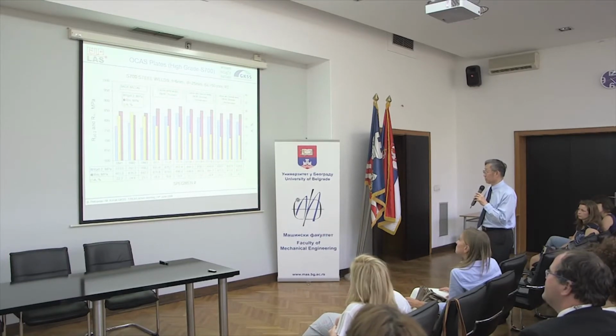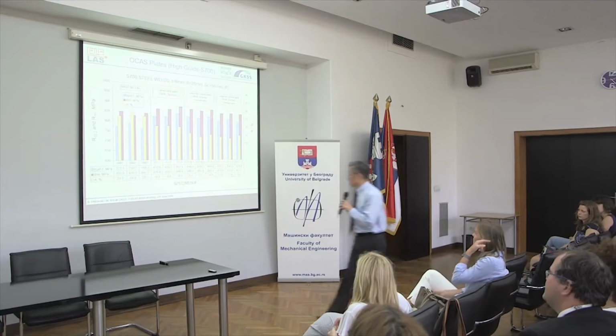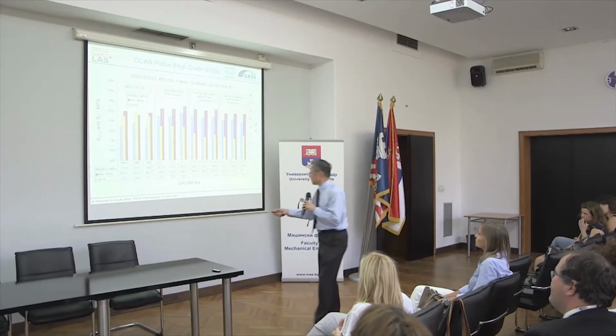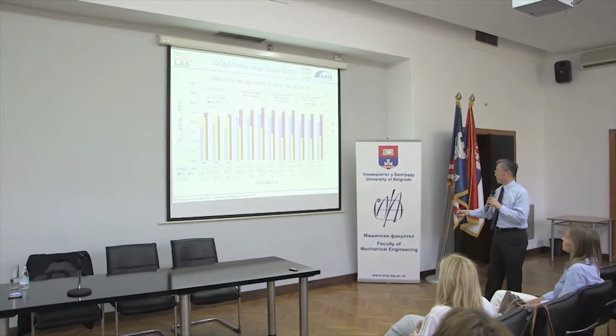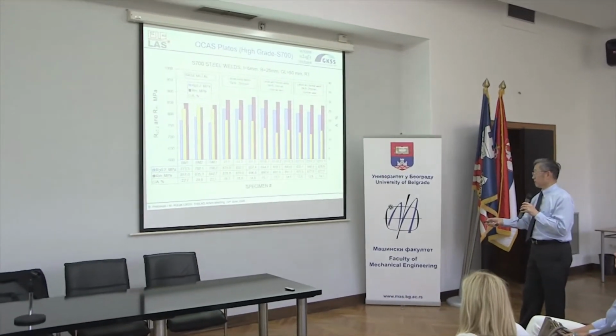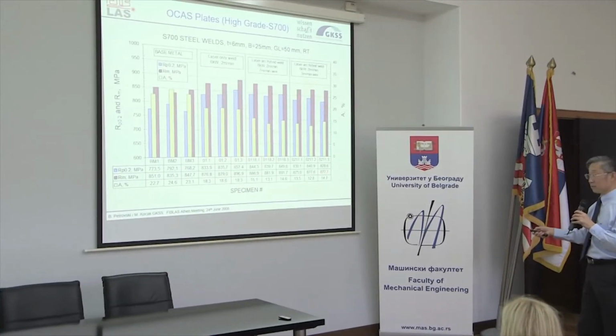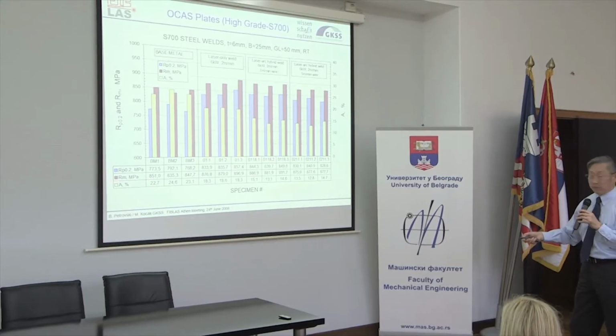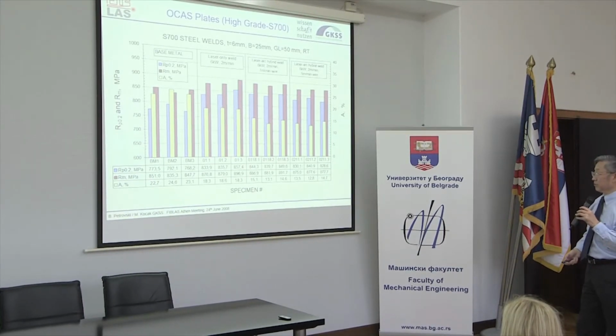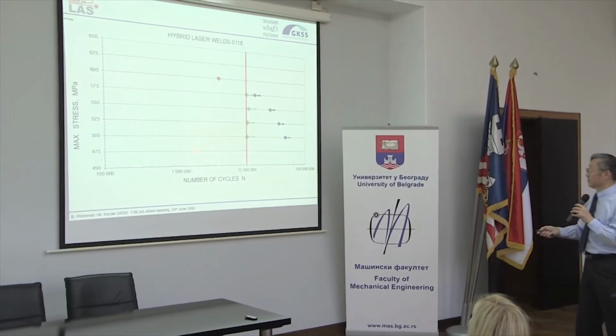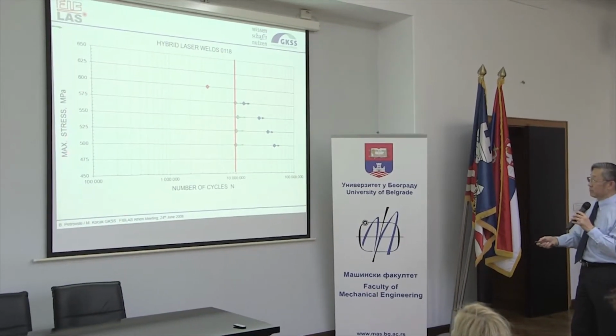Here are base metal and different kinds of welding procedures. Base metal, three specimens, then laser-only weld. Is this the ultimate tensile strength? Yes, ultimate, 850. So your loading is evidently lower than this value. Okay, let's go to the other slide, the previous one. You see, 500. So this is the maximum; the stress ratio is 0.1.